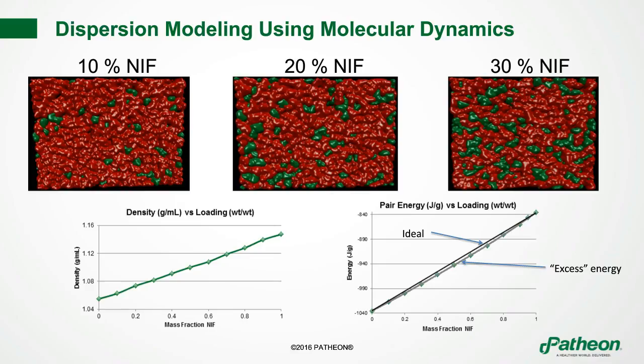The 20%, you can start to see that while you still have primarily drug that is very well dispersed, you've got some situations where you've got maybe one or two drugs that are close to each other. Now, if we were to change the drug from nifedipine to another drug like dipyridamole, you might actually see a decrease or an increase. We don't know, we'd have to run the simulation, but you might see a decrease or an increase in the amount of drug that is agglomerating. And that has to do with, like Tom was saying, the complementarity between the polymer and the drug.